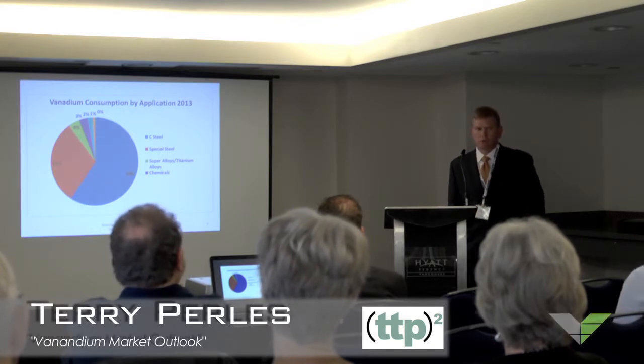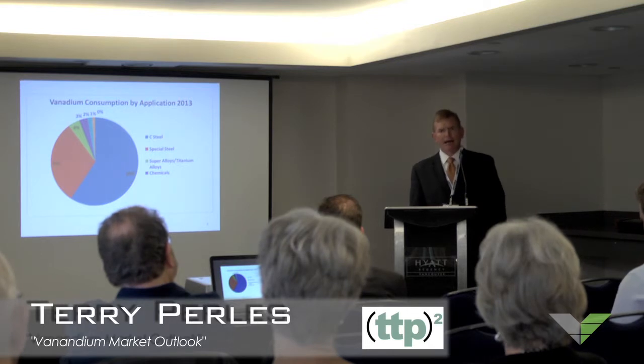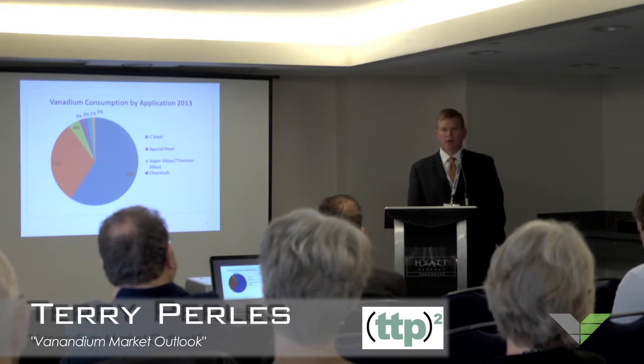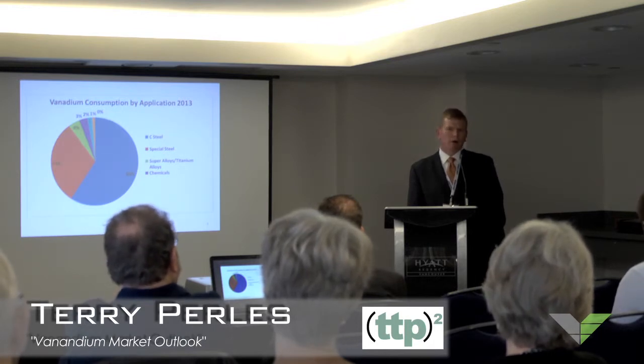Also in the steel industry, there's a significant amount of vanadium consumed in high-alloy steels. These are, for example, tool steels or high-speed steels that in many cases will have vanadium content from 1 up to 10 or 15%. Outside of the steel industry, the titanium alloy industry uses vanadium. About 4% of consumption today is going into the titanium alloy industry. These are alloys that are used primarily in aerospace and defense applications. The workhorse alloy in the aerospace field is titanium 6-4, which contains 6% aluminum and 4% vanadium.